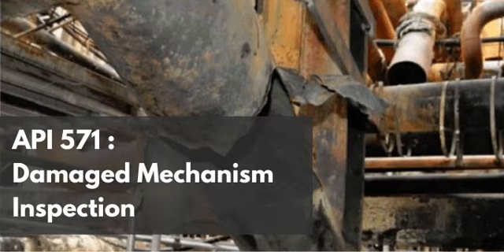When the molten steel solidifies and cools down, it shrinks. But the surrounding cold plates restrain that shrinkage. Because they're locked in place. Right. The result is that the weld joint locks in severe residual tensile stress. The metal is constantly pulling against itself with this invisible force that often approaches the actual yield strength of the material.